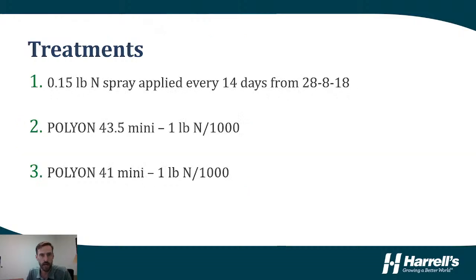The actual treatments that were applied were either the control, which was 0.15 pounds of nitrogen, spray applied using a 28-8-18 soluble fertilizer on a 14-day interval; Polyon 43.5 mini, applied at 1 pound of nitrogen per 1,000 square feet as a single application at the beginning of the trial. 43.5 mini is our thinnest coated material. It's our fastest releasing material. And a final treatment being Polyon 41 mini, applied at 1 pound of nitrogen per 1,000 square feet. Polyon 41 mini, as far as our mini size products go, these are SGN 120 to 150 type products. 41 mini is our slowest releasing material because it's our thickest coated mini material. Again, the thicker the coating, the slower the release.